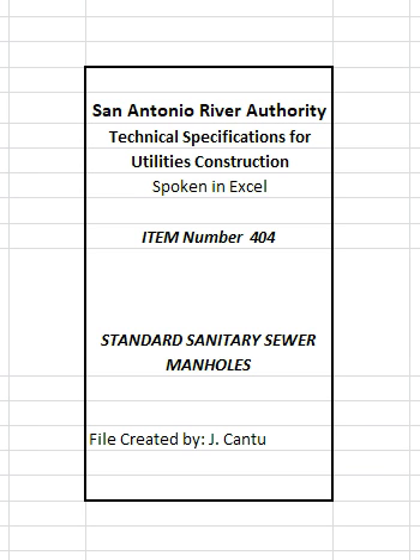Additional water may be added over a 24-hour period to compensate for absorption and evaporation losses. At the conclusion of the 24-hour saturation period, the manhole shall be filled to the top of the manhole cone and observed. Any loss within a 30-minute period shall be considered an unsuccessful test.